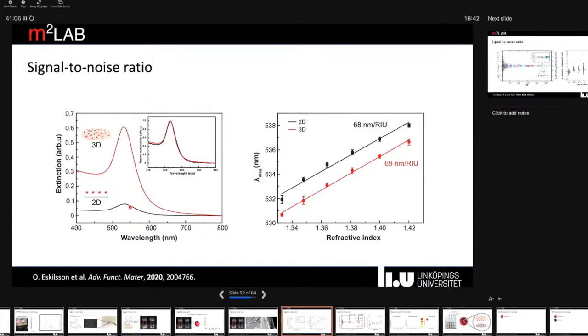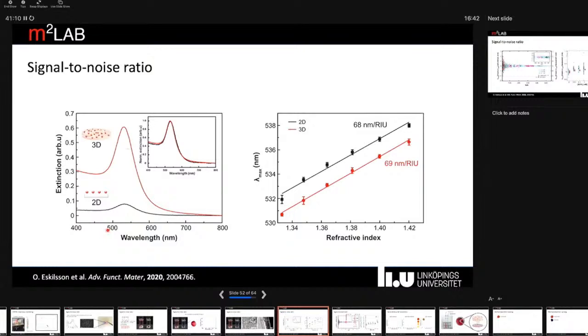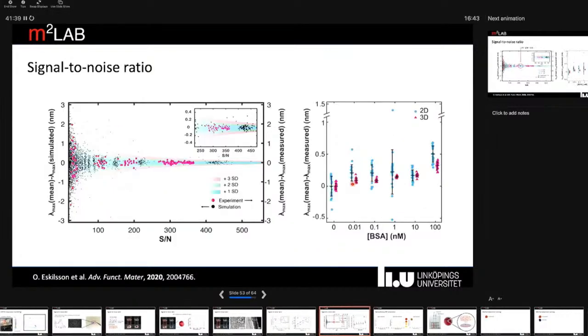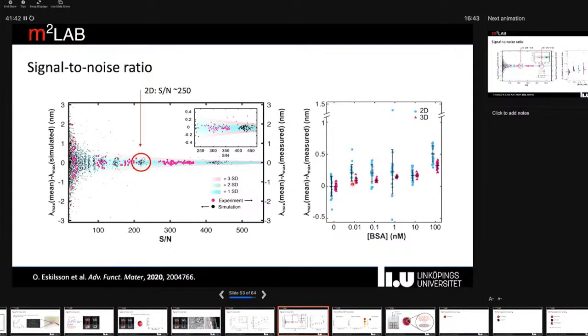And when we compare the intensity between these three-dimensional materials and the two-dimensional, we can see that there's a quite substantial difference here. But if we normalize the data, we see that there are no shifts or broadening of the curves. So essentially we have the same figure of merit. And this is also because there are no differences in refractive index sensitivity here. So what this means is that we increase the signal to noise. For the 2D surfaces, we have a signal to noise ratio roughly around 250, whereas in this case, it's substantially higher, around 450.